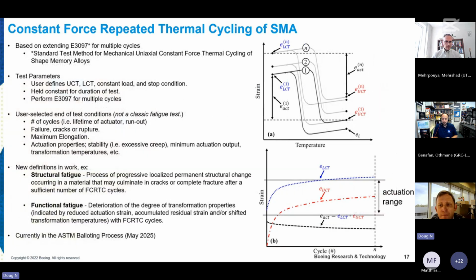Now, with shape memory alloy actuation, we could have failure because we evolve outside of our actuation range, for example, right? So that's not traditional failure or fatigue, right? But we want to consider that and quantify it. So we are developing those definitions as well within this test method. So for example, structural fatigue, right? This is our conventional fatigue and fracture. So process of progressive, localized, permanent structural change occurring in a material that may accumulate in cracks or complete fracture. We're also considering functional fatigue, right, which is the deterioration of the degree of transformation properties. So it could be reduction in actuation strain, shifted transformation temperatures.